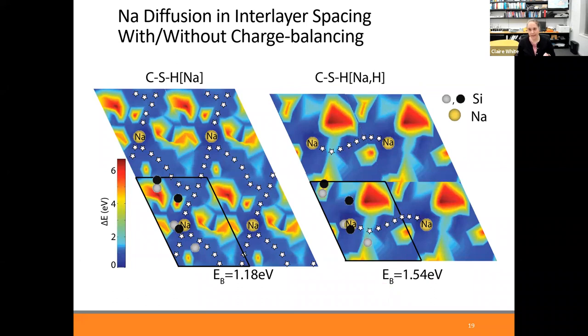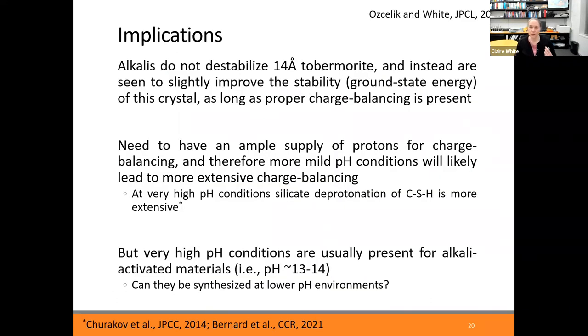So this is indicating that you can add sodium to the system, so you can have a sodium containing gel. If you have a sodium containing gel, you can get a gel that probably will perform in a similar manner to a CSH gel, so long as you have hydroxylated regions within the material. What I mean by that is having the hydrogens present that are bonded to oxygens. So you need to have an ample supply of protons for charge balancing to form these hydroxyl units.